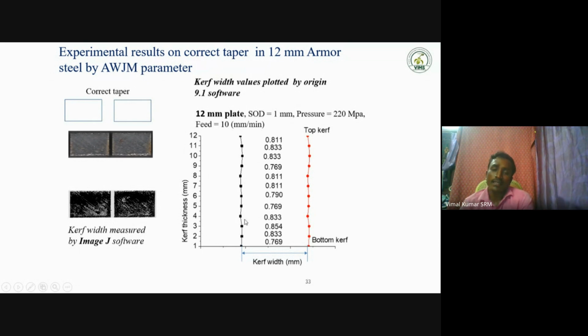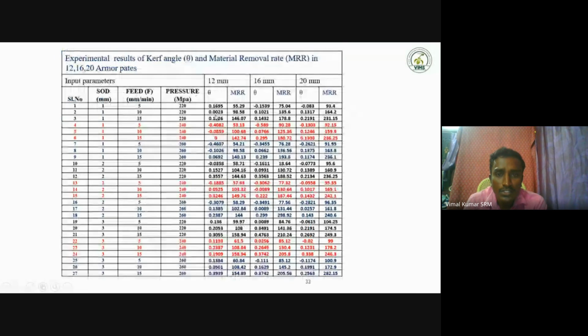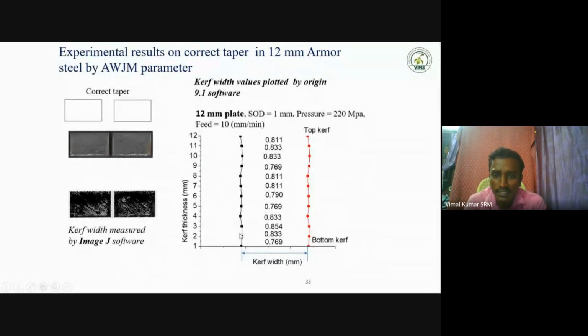That is the reason the kerf angle value is what I already showed, 0.0023. Why does 23 come here? It is because of this condition. Our eye cannot see the exact value; it is visible only when we zoom in. This kind of shape is what we really achieve. But this is also good, because to our eye it looks like a straight cut, but the ImageJ software can exactly predict the shape of the cut surface in the 12 mm thickness plate.